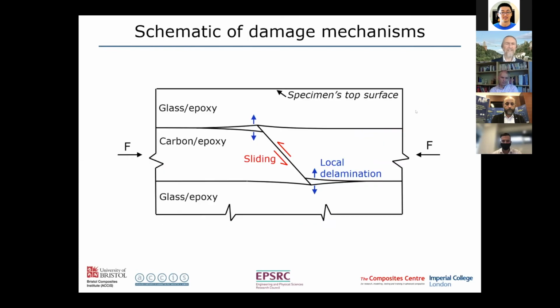So showing that schematically, we have the crack, which is typically at some sort of angle, and it's not a nice smooth crack like that, but conceptually we have a crack and some sort of behaviour where it can slide, albeit with friction and resistance, and then here we have a potential delamination opening up. But provided we keep this ply relatively thin, then there will not be initially enough energy to make that crack propagate. So this will be stable. But at a certain point, and especially it depends on the ply thickness, this may propagate. And then we would get an unstable failure.